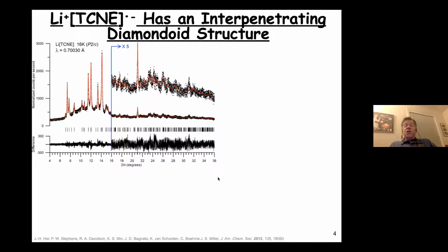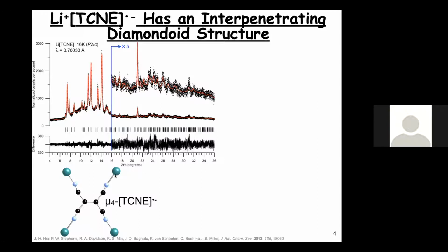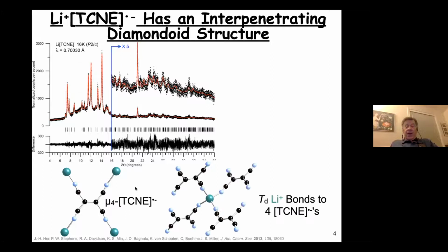The structure was solved by powder X-ray diffraction Rietveld analysis. The data and fit are shown here in the upper left-hand side. The analysis of the data shows that each TCNE radical anion, as predicted by the infrared spectra, in fact bridges to 4 lithium cations. Each lithium cation bridges to 4 TCNE radical anions.